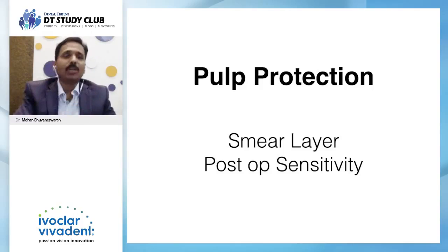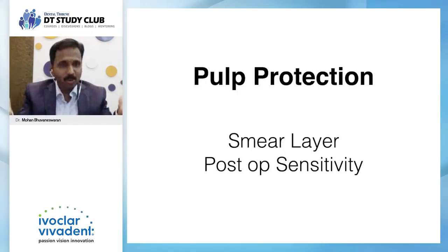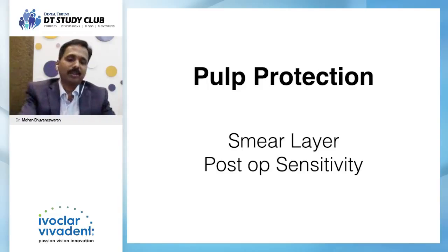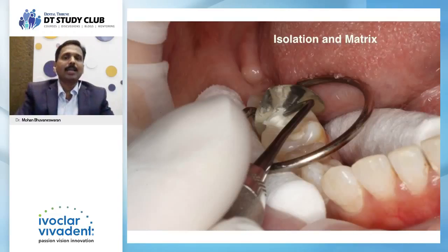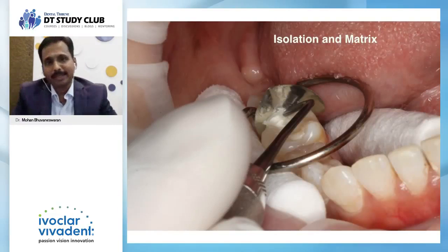And with regard to cavity preparation, I forgot to tell one point. We did come across one or two restorations which got debonded. Sorry, I'm not supposed to use the term debonded, which came out because the cavity preparation was not retentive. So the mantra is make the cavity preparation very retentive.